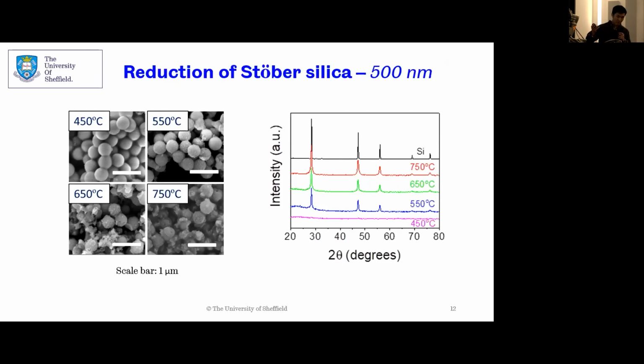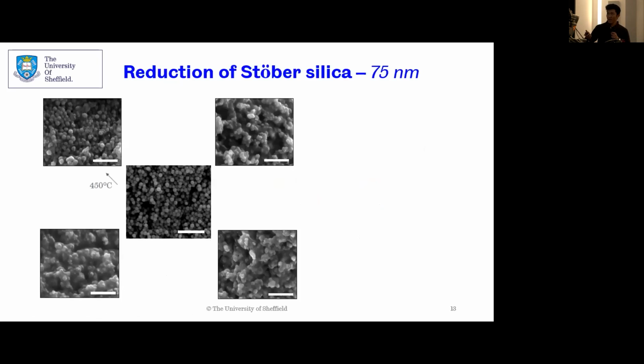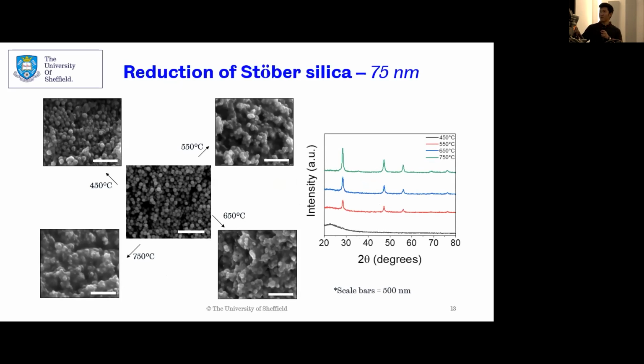450, no silicon. So 500 nanometers is too big to react at that temperature. 75 nanometer particles, I found the same thing. So anything above 550 degrees Celsius produces crystalline silicon, but 450 degrees Celsius does not. It might look like there's something happening there. I don't know why this is, but I also gold coat the particles, so that could be what I'm seeing there. But XRD shows that there's no crystalline silicon anyway.